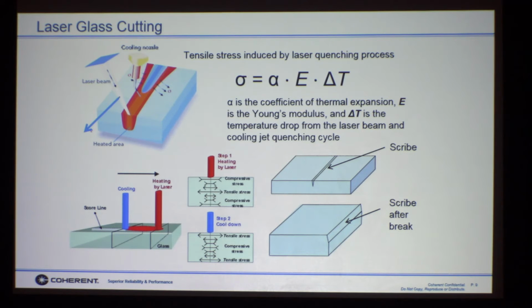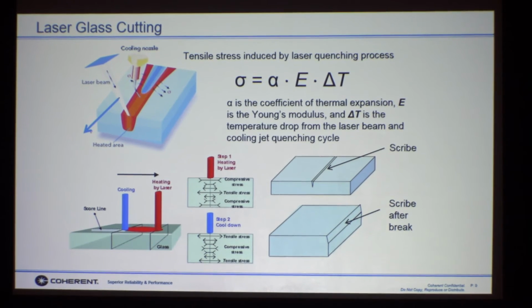We're going to talk about how to cut glass with CO2. Typically, you need to create tensile stress induced by a laser quenching process when you're cutting with CO2. What that means is you take a laser, heat the glass up, and then follow it by a cooling jet. That creates a scribe or a vent in the glass, in thicker glass, for example, anything above half a millimeter. And then later you mechanically break that glass.